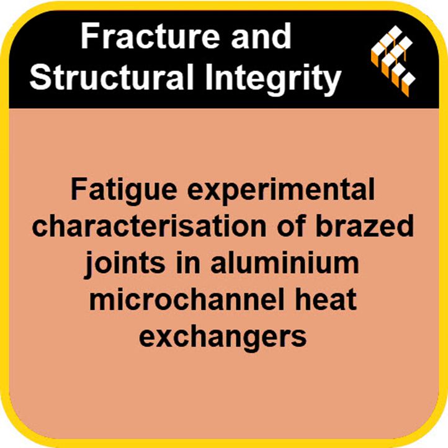Oh, yes, very much so. They observed the classic features you expect to see in high-cycle fatigue failures. Like what? Well, first, the crack clearly started right at the surface, which is typical when you have a stress concentration like that fillet toe acting as the trigger. Then, as the crack grew slowly with each stress cycle, you could see features often called ratchet marks or beach marks in the propagation zone. They look like tiny tide marks, really, showing the crack front advancing incrementally. And finally, the remaining material eventually couldn't take the load anymore, and you see a different texture in the final rupture zone, signs of a rapid overload failure, often ductile tearing in this kind of aluminum alloy. Standard fatigue progression.